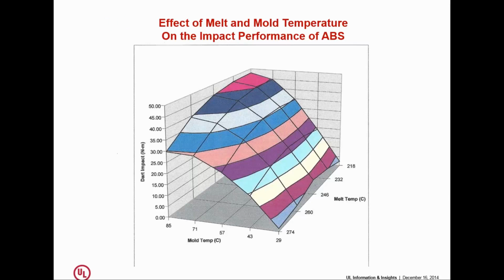One of the corollaries of running a melt temperature too high is that usually what goes along with that is people are running their mold temperature too low, and they're doing that to try and get the heat out faster. And what you'll notice here in this graph is that mold temperature in particular has a very dramatic effect on the impact strength of the material. The warmer the mold, the tougher the part, because a warm mold produces a part with less internal stress. Cold molds may look like a good idea for cycle time, but they produce a material that does not have everything it's supposed to have.